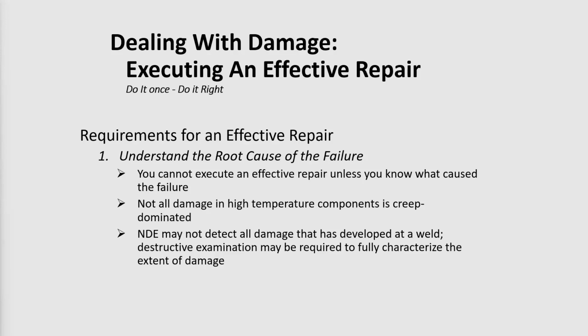It's very difficult to carry out an effective repair in a particular area if you don't know what caused the failure. The reason is that, particularly where creep damage is involved, if you don't understand the root cause of the failure, it's very likely that you will not be accurate in determining how much of the material needs to be excavated in order to accomplish the repair.